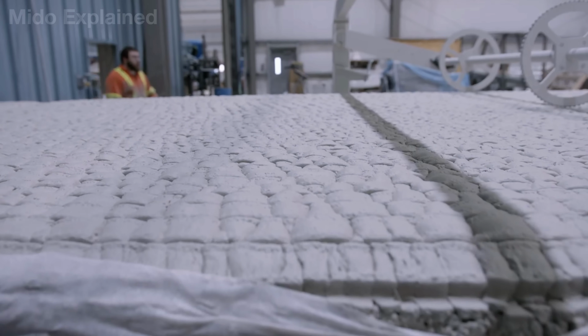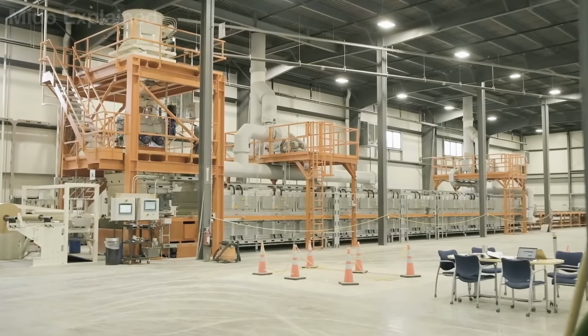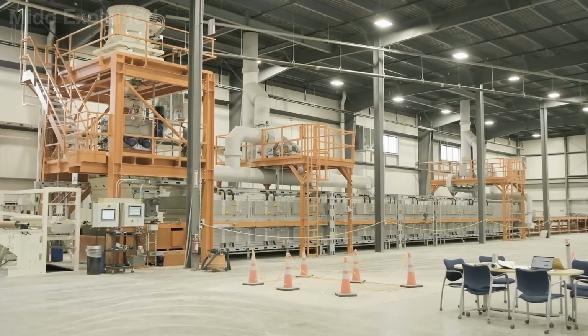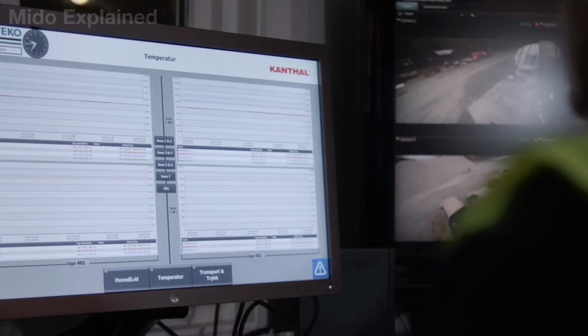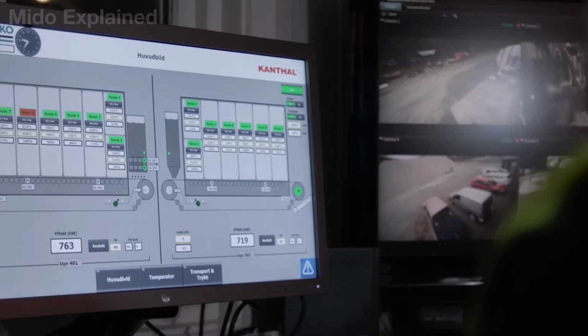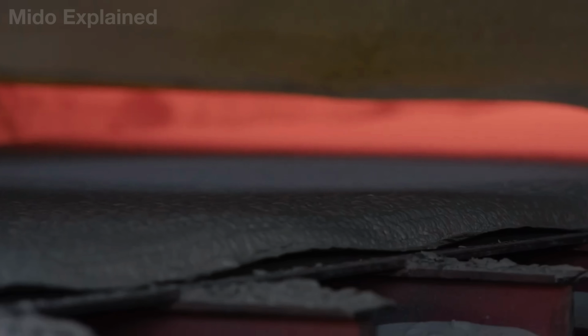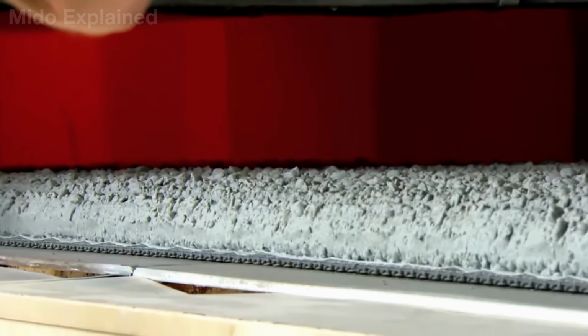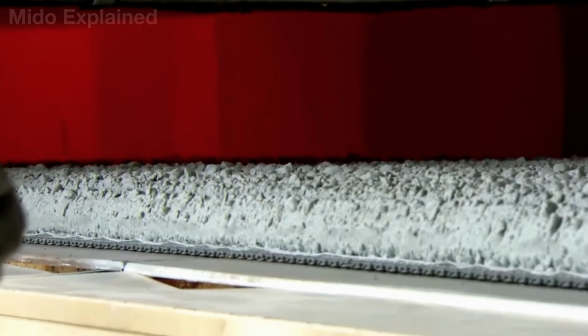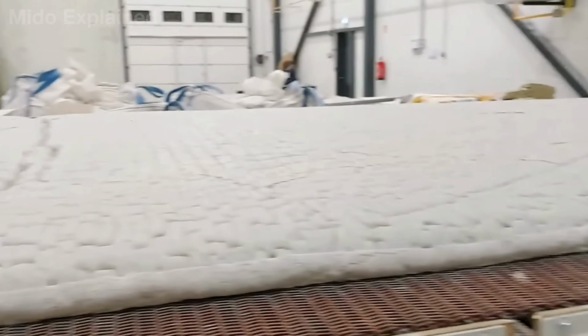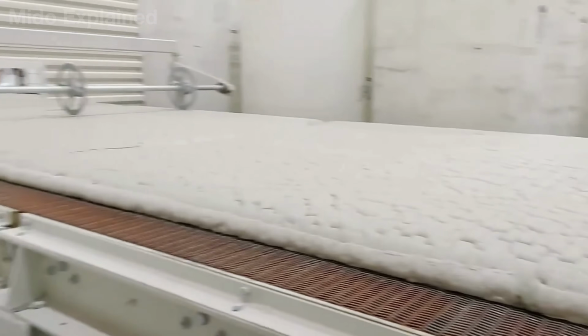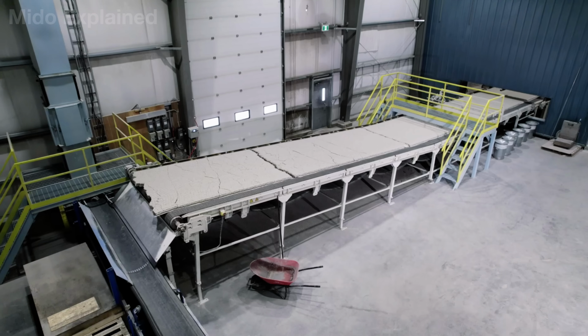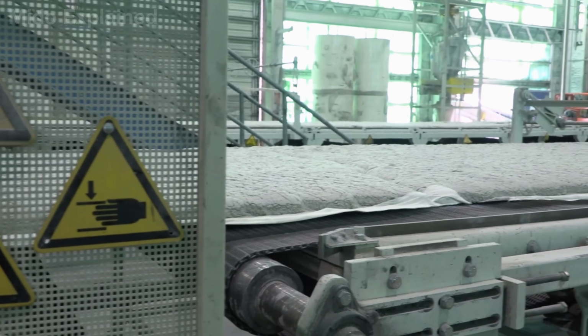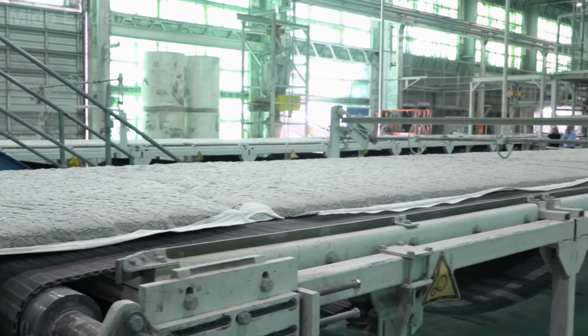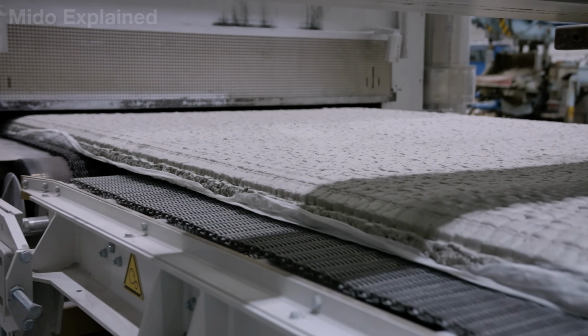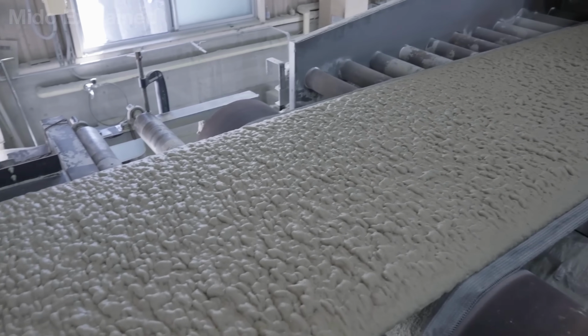The entire foaming cycle typically lasts about 45 to 60 minutes. During this time, the temperature must be controlled with extreme precision. Upon exiting the furnace, the material has expanded many times its original volume. The result is a complete foam glass block containing millions of sealed air cells inside. This finished product is significantly lighter than conventional concrete, but is still strong and durable enough to serve in industrial constructions requiring a lifespan of decades.